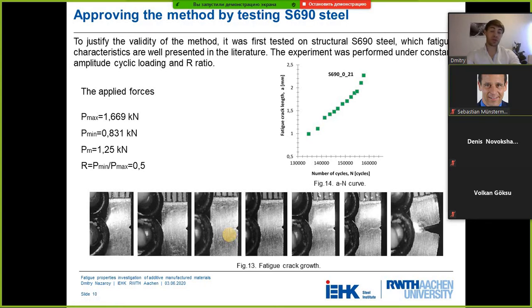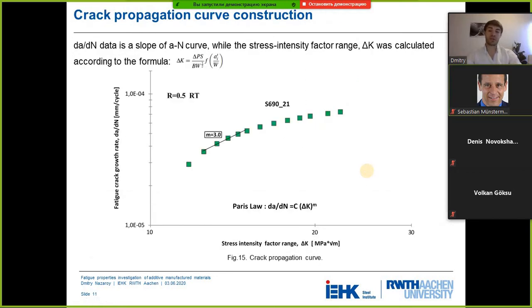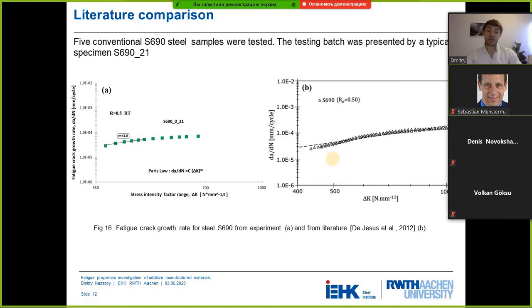The length was recorded with regard to the number of cycles, and it turned into the a-N curve, which is presented in figure 14. By taking the slope of this curve, da/dN data was received, and the stress intensity factor range was calculated according to this formula. Finally, we received the crack propagation curve for steel S690. These results were compared with the results in the literature, and the curves showed a similar trend. So the method was approved, verified, and ready for testing the fatigue properties of additive manufactured materials.